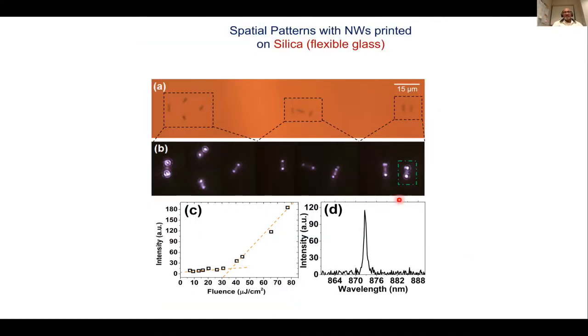So here's an example of the case where they have really transferred these onto a glass slide, a flexible glass slide, so that they could be used for flexible optoelectronics applications. And then you can start seeing the light coming from both ends of the nanowire. Also, as you can see, the threshold-like behavior and a narrow line width show that even after transferring, these nanowires are lasing, indicating that this transfer process is a gentle process.